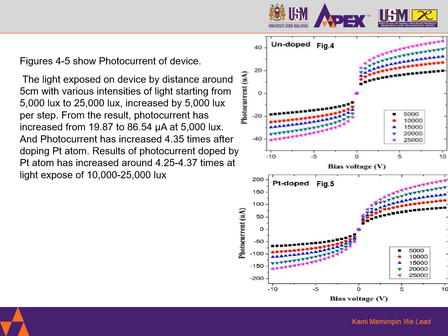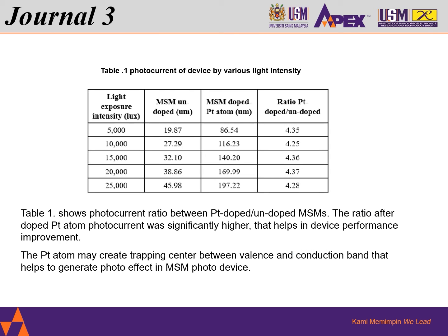Results of photocurrent doped by Pt atom has increased around 4.25 to 4.37 times at light exposure of 10,000 to 25,000 lux. Now, table 1, photocurrent of device by various light intensity. Table 1 shows photocurrent ratio between Pt doped and undoped MSM. The ratio after doped Pt atom photocurrent was significantly higher. That helps in device performance improvement. The Pt atom may create trapping center between valence and conduction band that helps to generate photo effect in MSM photo device.